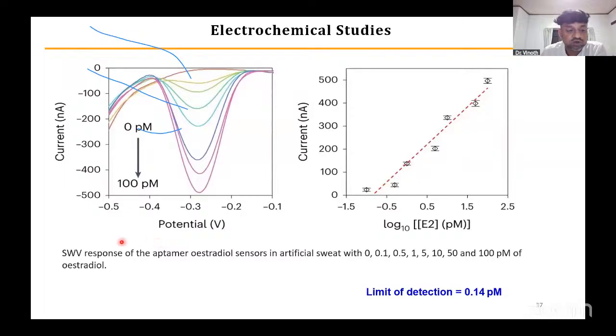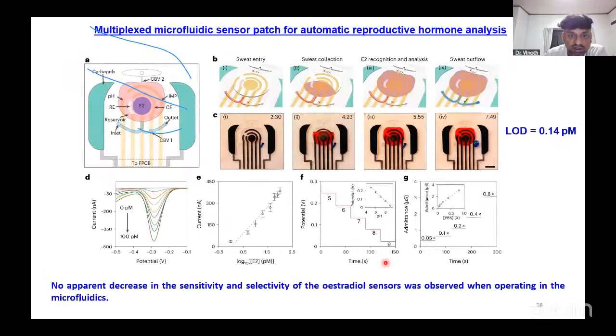Here we can see the square wave voltammetric response of aptamer estradiol sensors in artificial sweat, with concentrations of 0 to 100 picomolar of estradiol. Here we can see that as the concentration of estradiol increases, the peak current increases on the reduction side. Here we can observe clearly. So from this graph, we can make a linear plot, and we can find the limit of detection is 0.14 picomolar of estradiol in artificial sweat.